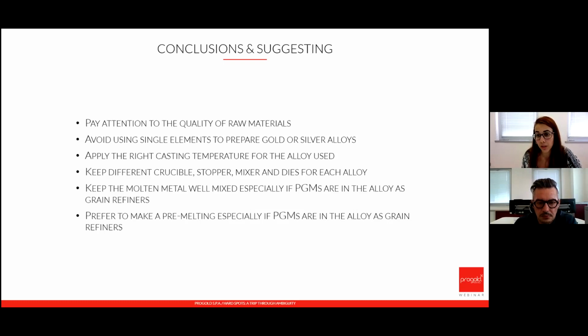It also depends on the conditions of the casting, because if you have an open casting machine, the melt is going to react with oxygen, and the higher the temperature, the more favorable the reaction with oxygen will be. So the longer you leave it, the more oxides you're going to get inside. If you have a closed machine, where the bath is protected with argon or nitrogen, chances are that you can leave it longer.